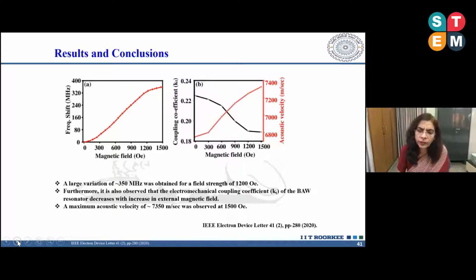A large variation of 350 megahertz was obtained for a field strength of 1200 Oersted. The frequency shift seen in this piezo resonator for 1200 Oersted was 350 megahertz. A maximum acoustic velocity of 7,350 meters per second was observed at 1500 Oersted.